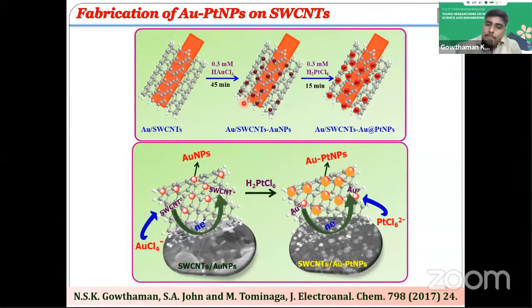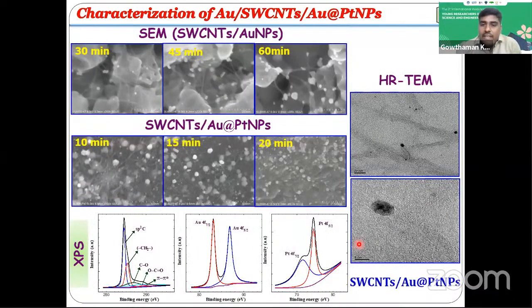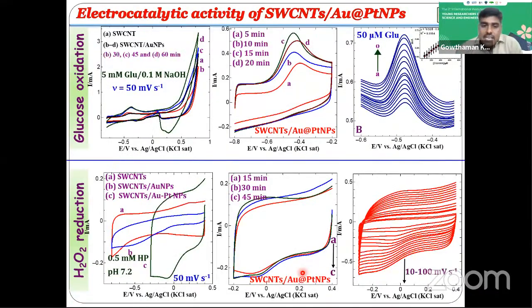Likewise, the Au nanoparticle-formed electrode is immersed into the chloroplatinic acid solution. There is a formation of gold-platinum bimetallic core-shell nanoparticles on the electrode surface. We utilize the electrode for the detection of glucose and hydrogen peroxide sensing.